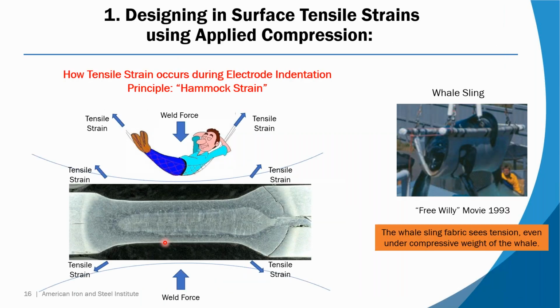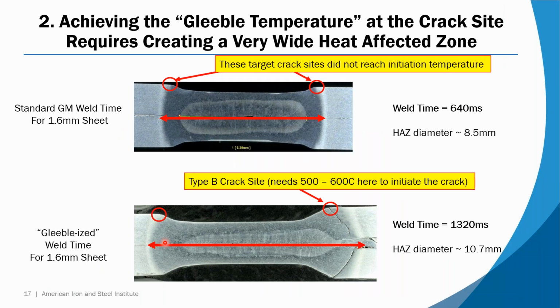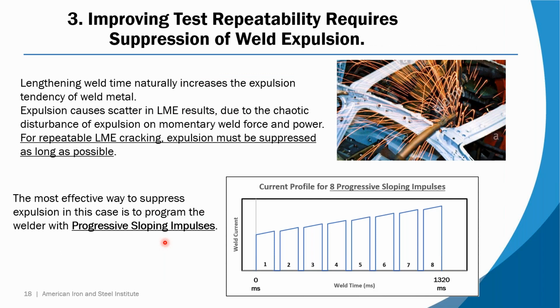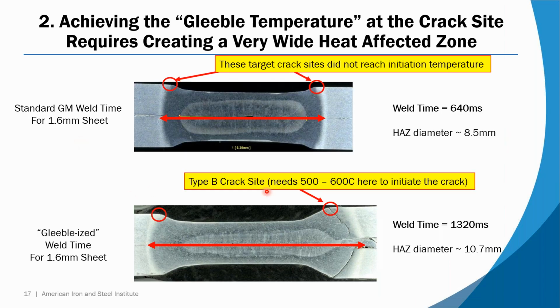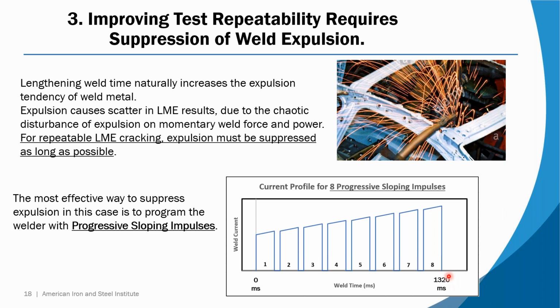No, we validated these parameters when we developed them. We tested that range from 1.5 plus or minus 1/10 of a millimeter, and there's no need to change the parameters. When you go to 1.0, we did have to change the parameters. Instead of 8 pulses on the thin material, we used 11 pulses. It's interesting because we want a similar heat affected zone diameter, but in a thinner sheet. When we weld the 1.0, we still have to get the heat affected zone to push out roughly the same distance. So the overall time, this is 1320, in the 1 millimeter material, is roughly the same because that's how long it takes heat to travel sideways to that diameter we're trying to hit.